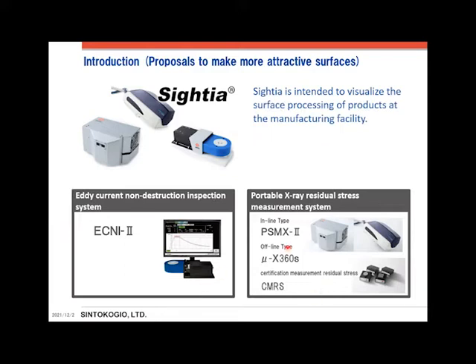The other is a portable X-ray residual stress measurement system that measures residual stress on the material surface. The PSMX2 is an inline type for field use, and the Micro X360S is an offline type for scientific purposes. And this figure shows the certified measurement residual stress, CMRS. CMRS is used to confirm the measurements taken by the X-ray residual stress measurement system are correct.